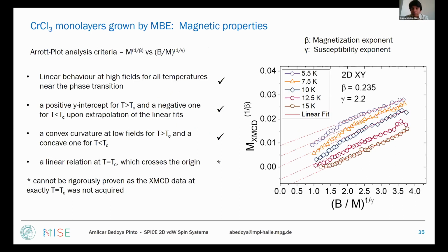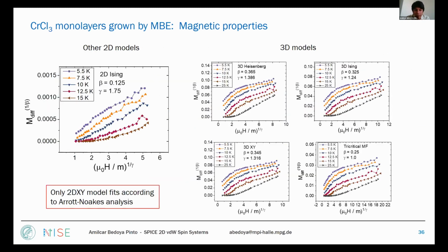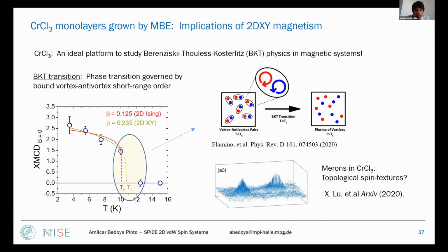In our case, maybe I leave it for the questions. People will ask how you determine that this fitting is consistent. There are many criteria that I could leave for the questions. I also tried to model it with other 2D models and 3D models, and none of them fit this critical scaling analysis. So we are pretty confident that the 2D XY model is the one we have in our system. Of course, the existence of this 2D XY is related to the BKT,